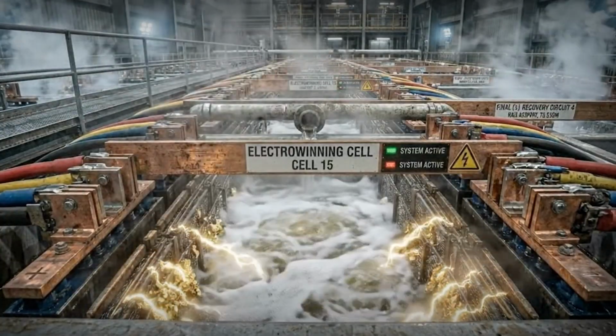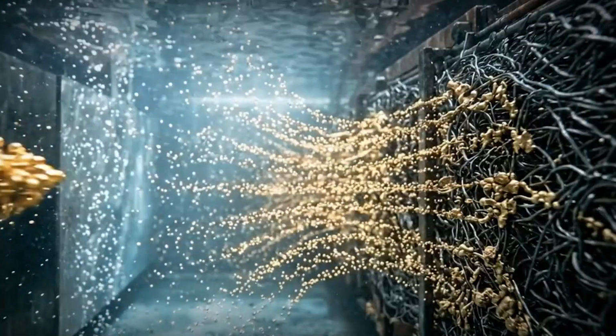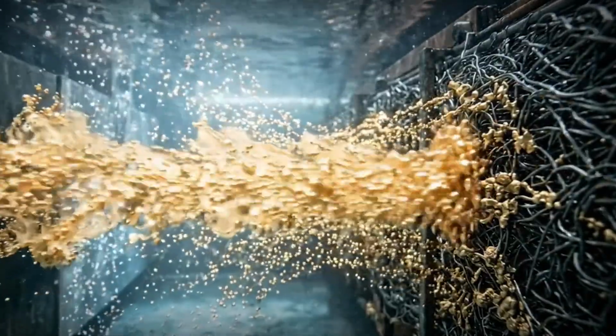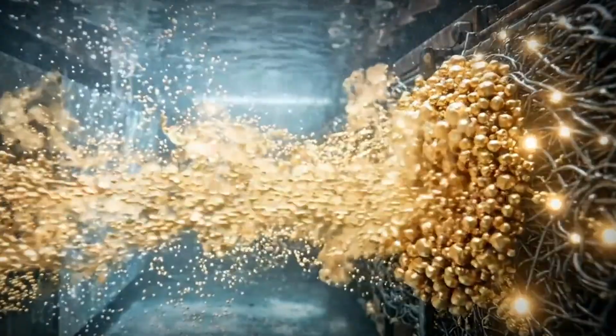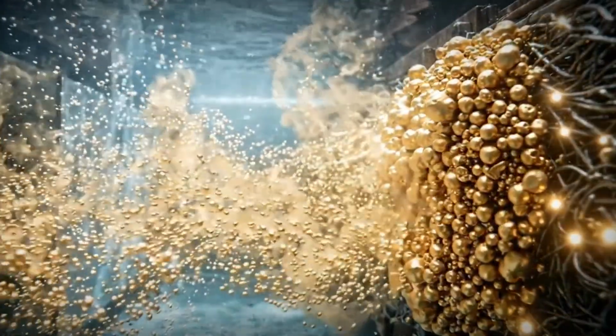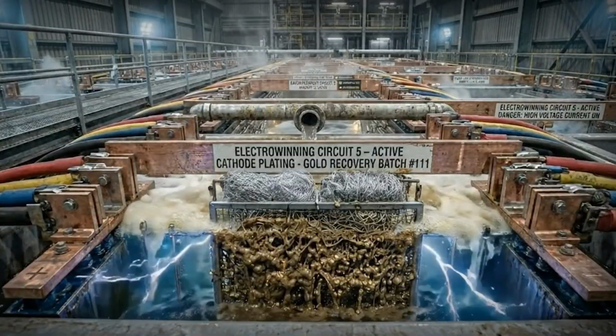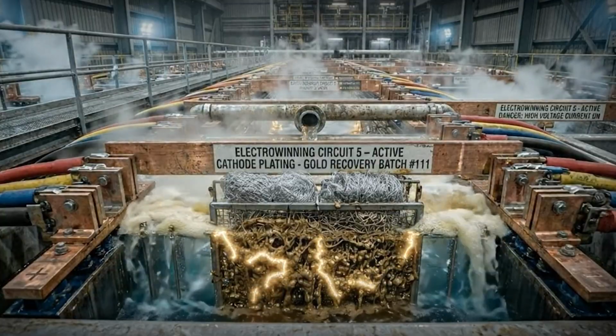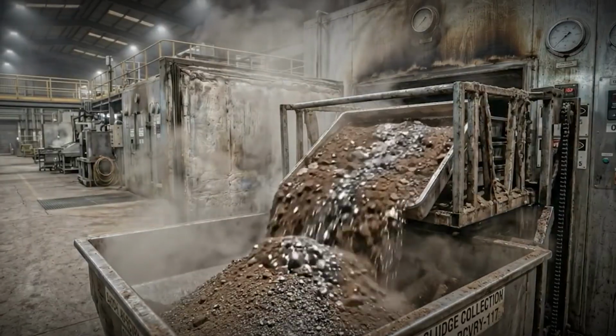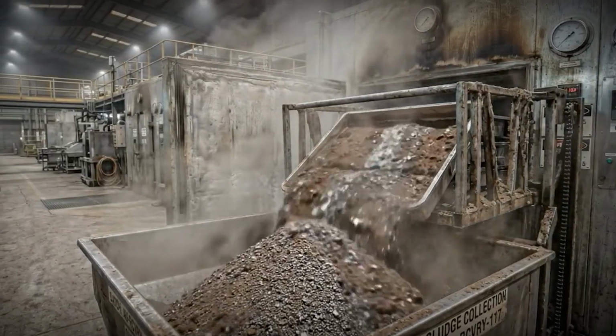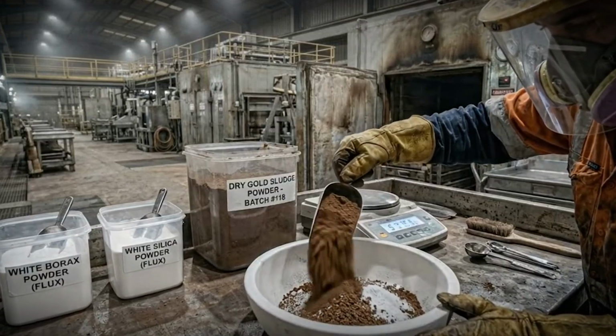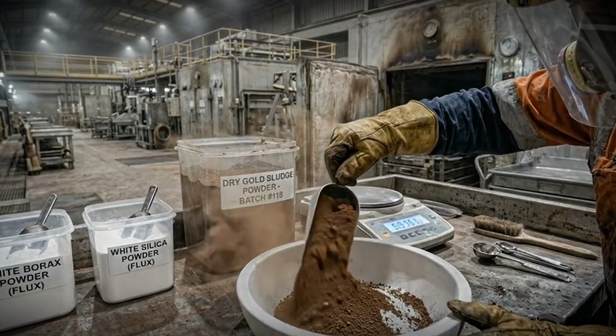The gold sludge is loaded into a smelting furnace heated to temperatures above 1064 degrees Celsius, the melting point of gold. Flux is a mixture of chemicals that causes impurities like silica, iron, and sulfides to separate and float to the surface as slag. The slag is poured off. What remains is liquid precious metal. This is poured into molds and cooled.